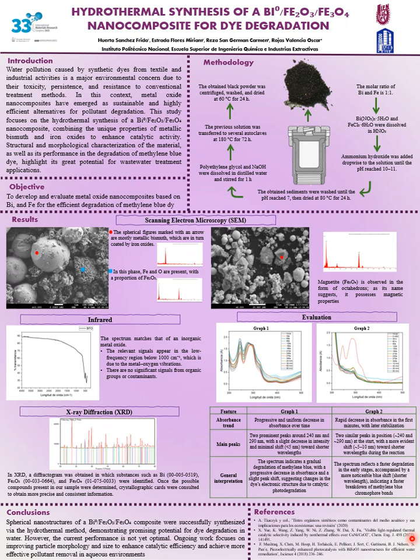Conclusions. Spherical nanostructures of a Bi/Fe2O3/Fe3O4 composite were successfully synthesized via the hydrothermal method, demonstrating promising potential for dye degradation in water. However, the current performance is not yet optimal. Ongoing work focuses on improving particle morphology and size to enhance catalytic efficiency and achieve more effective pollutant removal in aqueous environments.